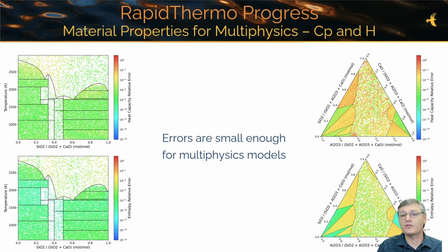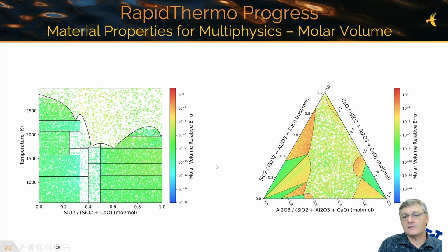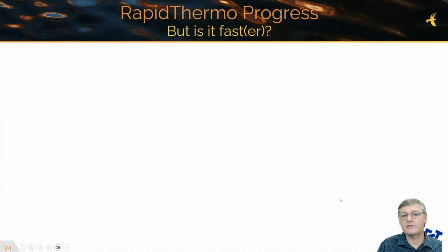So these errors are definitely small enough for use in multiphysics models. These models in most cases use constant material properties for their entire domains. RapidThermo makes it possible to vary composition and material properties throughout the domain. This is the first demonstration of another physical property, molar volume in this case, and you can see the errors between the direct calculation of a model based on ChemApp and the RapidThermo interpolation are small in the binary case, larger in the ternary case. Again, I think we have higher order interpolation problems that we can fix on the ternary side, which will make it even more accurate. But these numbers are already quite acceptable for use in multiphysics.